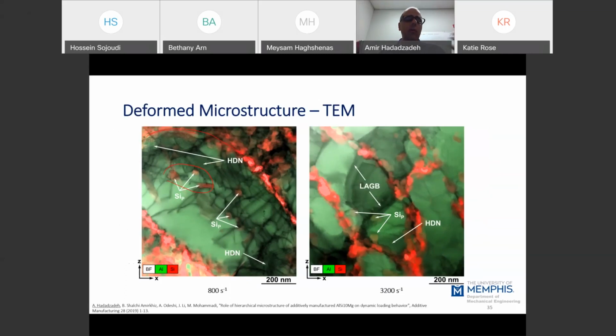So hexagonal dislocation networks will develop, which is a common kind of dislocation network in FCC materials. And these hexagonal dislocation networks, in presence of temperature, can rearrange, and low angle grain boundaries can evolve in the structure, as you see here. So this is a recovery process. So the initial hardening is related to generation of new dislocations. Then we had softening in the material by increasing the strain rate because we had recovery. So far, I was able to explain the initial hardening and softening.